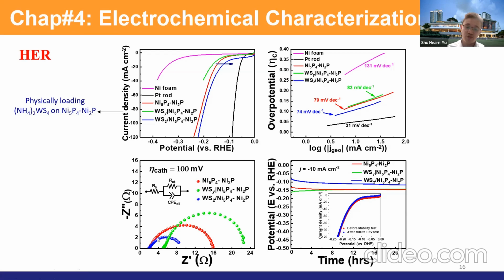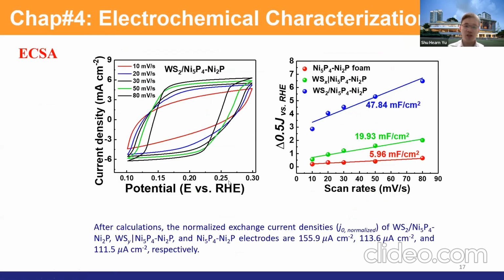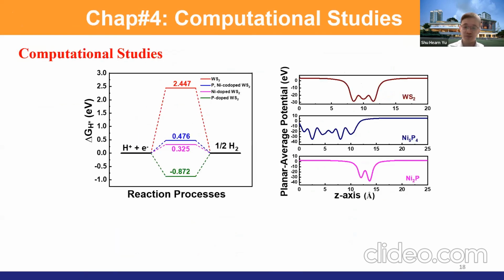And we also have a smaller charge transfer resistance from the Nyquist plot. We also test the stability over 24 hours in both the chronopotentiometric method and the LSV method. Then we measure the surface area, and we find that the surface area of the catalyst indeed increased. We also measure the turnover frequency, and the intrinsic activity of our hybrid sample indeed increased.